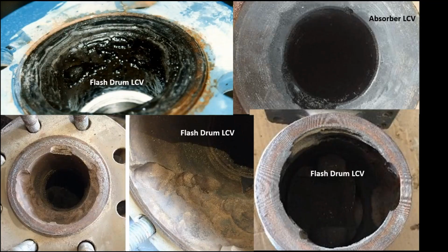These pictures all show corrosion damage on valve bodies downstream of an obstruction or on the downstream side of a level control valve. The upper right picture shows an absorber level control valve with some corrosive attack. All the other ones show quite major attack on the downstream part of the valve body. And the reason why the flash drum level control valves are much more severe as far as the corrosion rate goes is because that level control valve is downstream of the lean-rich exchanger, and the temperature is much hotter at this location, so any corrosive attack will be accelerated.